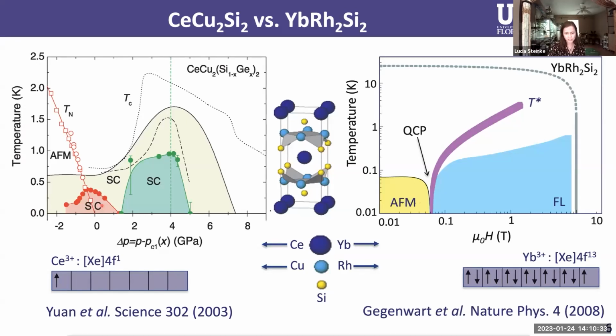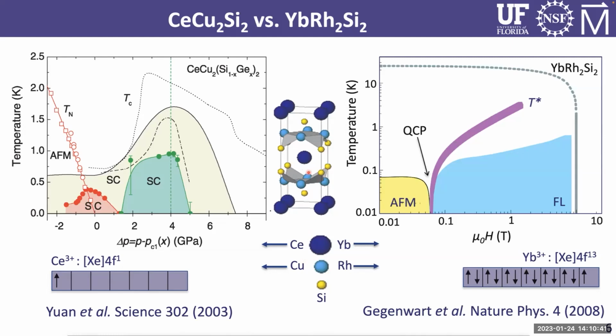What is odd here is that it's actually very similar to the original cerium copper two silicon two. It has the same crystal structure, except ytterbium replaced for cerium, and rhodium for copper. It's also magnetically quite similar. It just has one hole in the f shell instead of one electron.